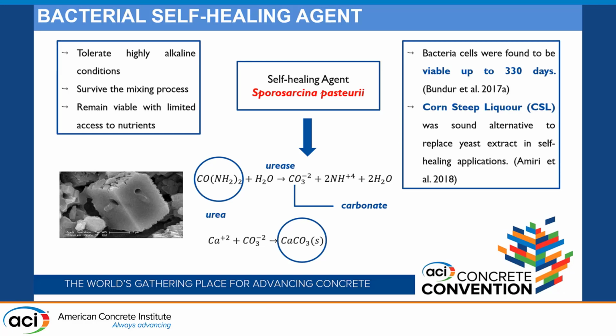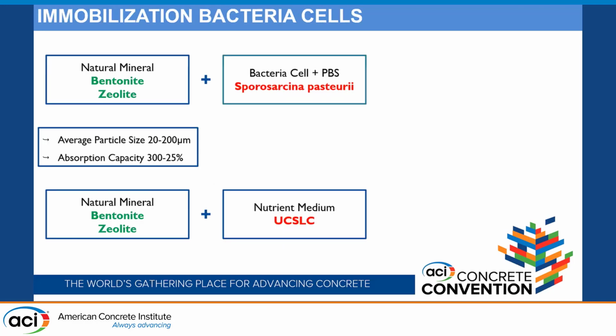In our previous studies conducted by Dr. Zeynep Başaran Bundur, Sporosarcina pasteurii cells were found to be viable for up to 11 months when directly added to the mixture, and this methodology affected the healing of cracks in seven-day-old samples. But limited availability of the nutrients and the lack of oxygen decrease the amount of calcium carbonate precipitation through the crack depth. Therefore, this situation led to different encapsulation methodologies. The encapsulation methods are based on embedding minerals in a protective covering such as natural minerals, polymeric membranes, lightweight aggregate, and so on.